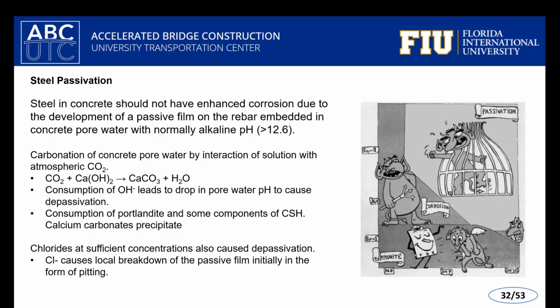So in terms of carbonation-induced corrosion, the major factor to break that devil free from that cage is actually the air that we breathe. The carbon dioxide in the atmospheric air can penetrate through the concrete cover, typically dissolves in the concrete pore water via Henry's law, and interacts with the calcium hydroxide, the portlandite that we find in the concrete pore water. It consumes the calcium hydroxide, consuming the hydroxyl ions, creating calcium carbonate as the end byproduct. Sometimes we see some efflorescence related to that. But importantly, the consumption of the hydroxyl ions causes the reduction of pH.